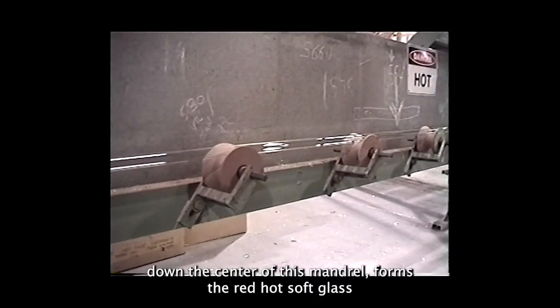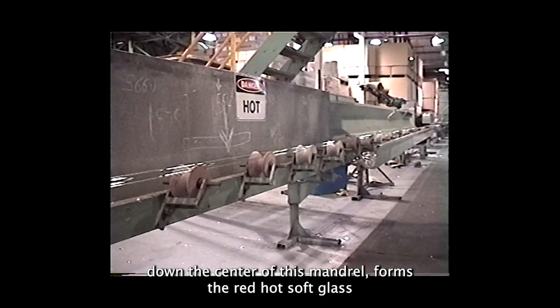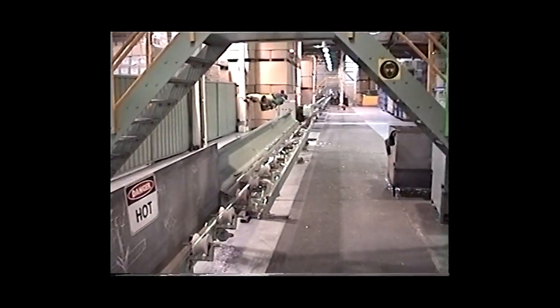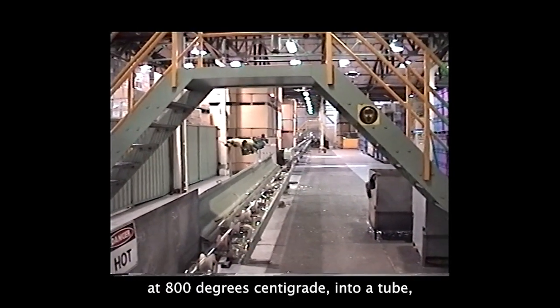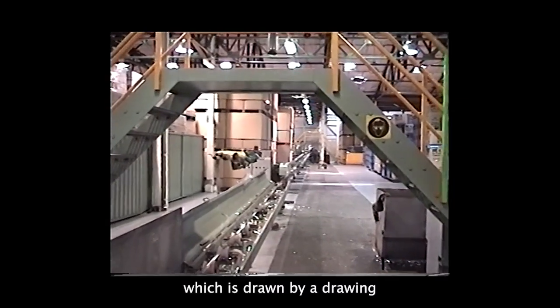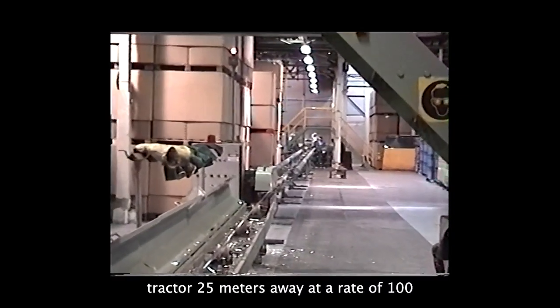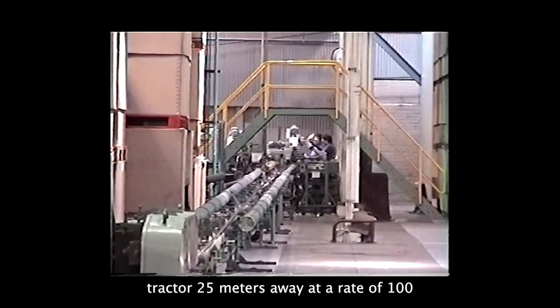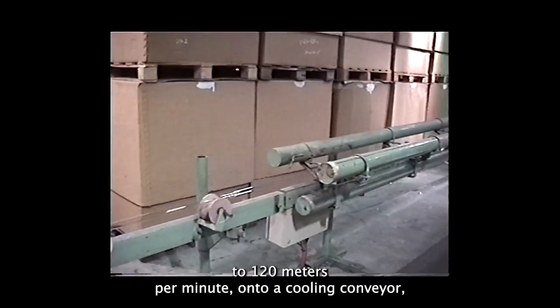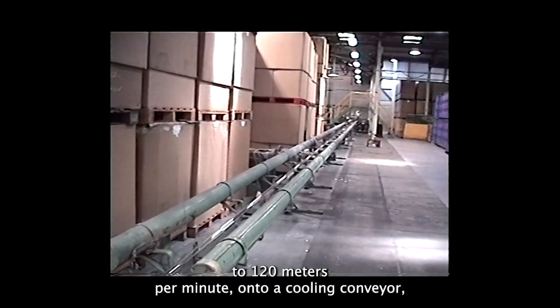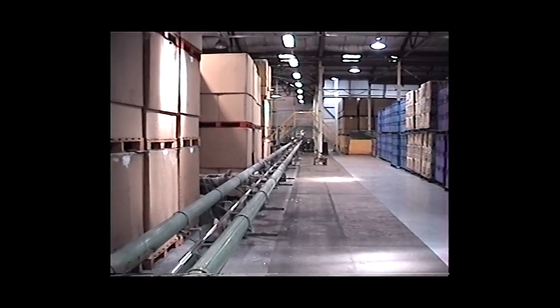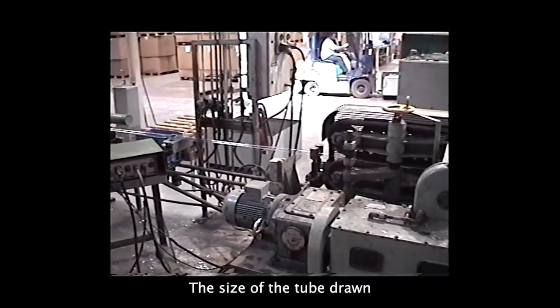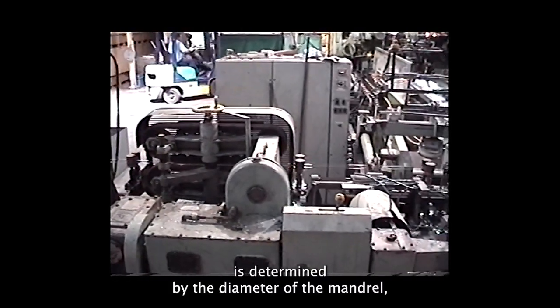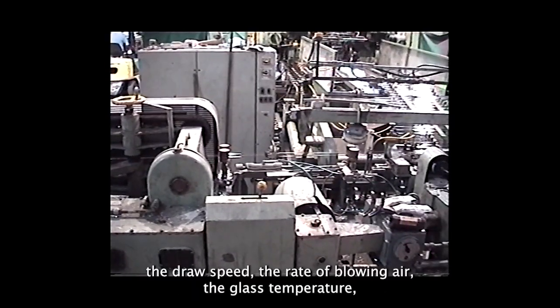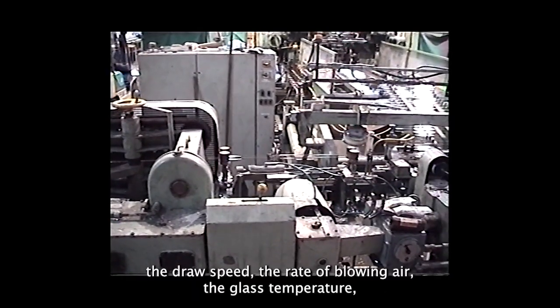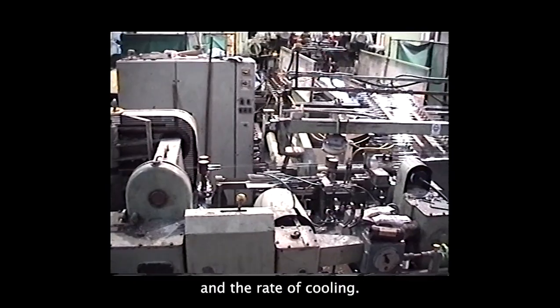Air blown down the centre of this mandrel forms the red-hot soft glass at 800 degrees centigrade into a tube, which is drawn by a drawing tractor 25 metres away at a rate of 100 to 120 metres per minute onto a cooling conveyor. The size of the tube drawn is determined by the diameter of the mandrel, the draw speed, the rate of blowing air, the glass temperature and the rate of cooling.